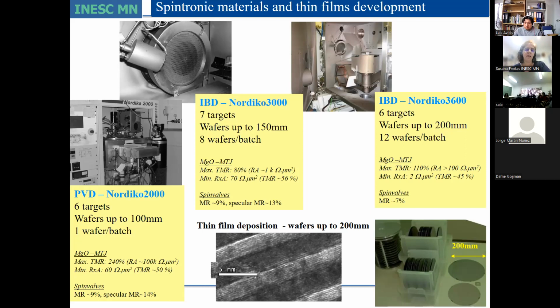For example, for the exchange materials, for the antiferromagnetic materials, they have different blocking temperatures, different thermal stabilities. So we had 2 companies in the last 2 years. They asked us to help them to optimize the blocking temperature for those materials. Because they wanted, for the bridge, if you want to repin, to create a bridge in the wafer, you need to have 2 sensors in one direction and then 2 other sensors in the 180-degree direction.